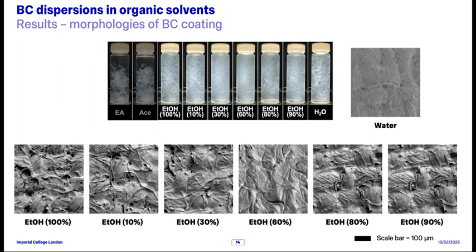However, when the bacterial cellulose coating was applied from a more homogeneous bacterial cellulose dispersion, a better bacterial cellulose coverage and hence fewer defects resulted. But very unexpectedly, we also noticed that the bacterial cellulose coating applied from BC in water dispersion does not possess the highest coverage. But in fact, the BC coating applied from a BC in 60% ethanol-water dispersion has the highest coverage, whereby all the pore openings of the woven fabric are fully covered.